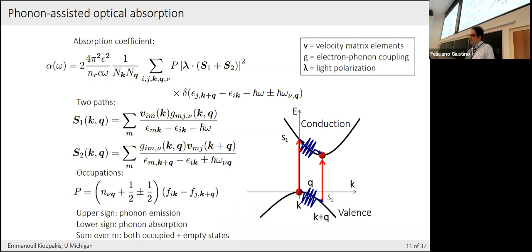And usually when we talk about semiconductors, the band gaps involved are of the order of electron volts. So the photon always gives us enough energy in order to emit the phonon and make this process possible. And so what I find surprising is that phonon-mediated processes are possible even at absolute zero temperature. And in fact, they're actually quite temperature insensitive, because you can always emit a phonon, and the phonon emission term is not so dependent on temperature. So that's kind of counterintuitive for a phonon-mediated effect.